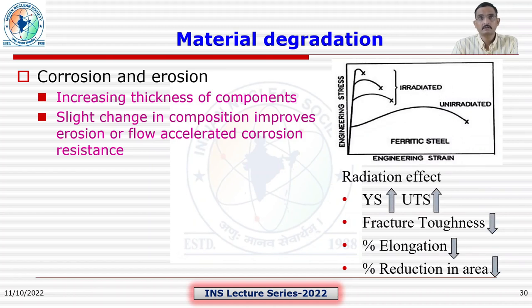Another degradation in core components, especially in nuclear power plants, is change in material properties mainly due to neutron irradiation. It basically increases the yield strength and ultimate tensile strength of the material, but it decreases the fracture toughness and overall toughness of the material. You can see in this figure that the yield strength of the material increases drastically after irradiation, and the toughness of the material decreases.